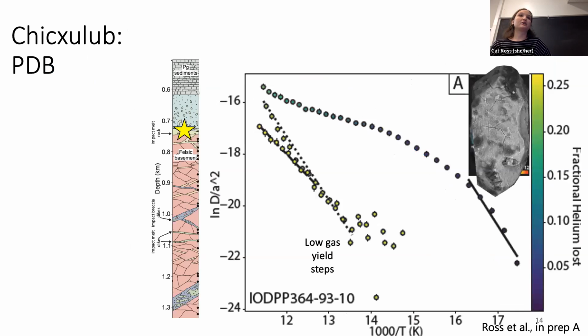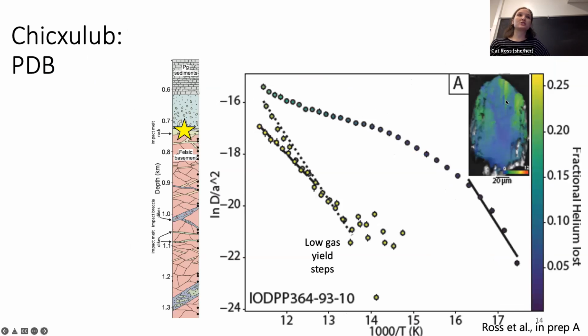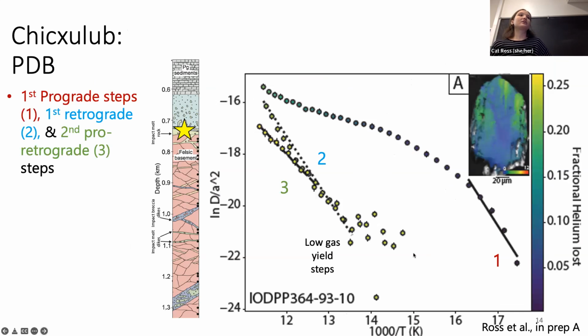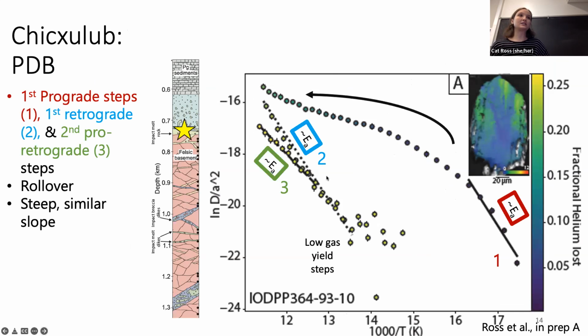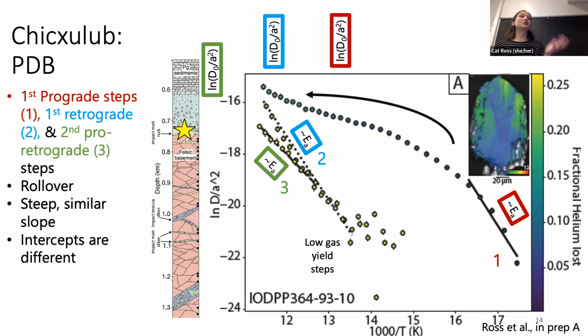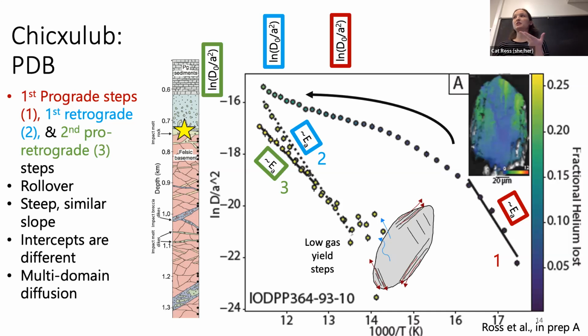In the case of a grain that has planar deformation bands, you can see in green here, we have a couple of different best fit lines we can plot through the data with a rollover in between the first and second best fit lines. They have similar slopes, but very different y-intercepts. So this is indicative of multi-domain diffusion. You're diffusing out of the smaller domains, they degas first, and then a larger domain second.